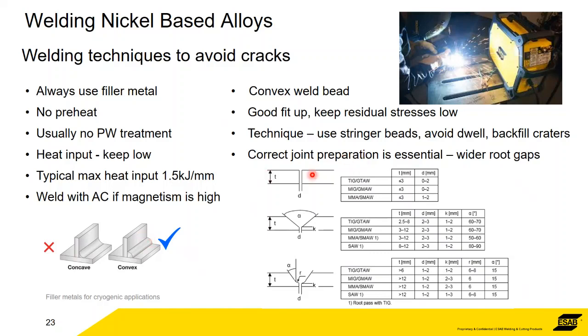And again, something that we've said before about stainlesses and duplexes, and it's very relevant for the nickel-based alloys, is joint preparation. So before you even start welding, it's essential to design the joint such that it has wider root gaps. As a rule of thumb, generally, the more highly alloyed the filler metal is, the less it wants to flow. So the fluidity of the weld pool is not very good. It doesn't want to flow.